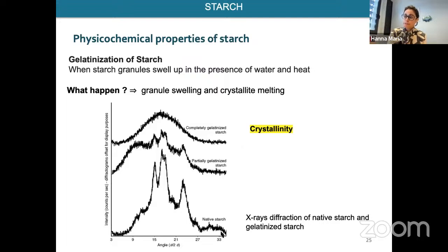We have first the native starch. So you can see the peaks that are related with the crystalline zones of the starch, and they are characteristic of the starch. And then with the partially gelatinized starch, you see that the intensity of these patterns starts to decrease. And when we have the complete gelatinization of starch, you see this pattern. It means that it's an amorphous polymer.